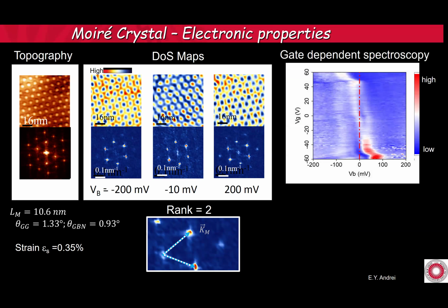And then when you do a dI/dV map, which means every horizontal line is a fixed gate voltage, a fixed doping, and you vary the bias voltage, you typically go along a horizontal line. And you see, this is our flat band, which is roughly the same flat band as you see without the boron nitride. And you see that as the Fermi level goes through this band here, you open gaps,